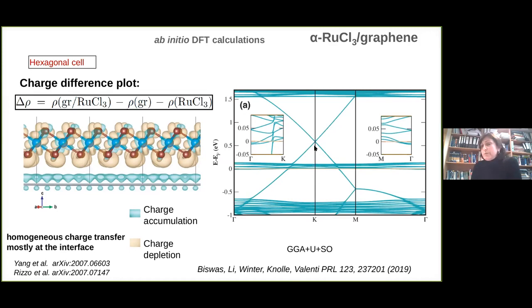Moreover, if we look at the electronic structure of this heterostructure, at the K point, where we used to have the Dirac point of the graphene, graphene is now hole-doped. Here is our Fermi surface, and the ruthenium trichloride bands form almost flat bands around the Fermi level. One can distinguish two types of Fermi pockets. At the K point, we expect hole pockets of graphene, and at the gamma point, we expect electron pockets of ruthenium trichloride. So this is the theoretical prediction.